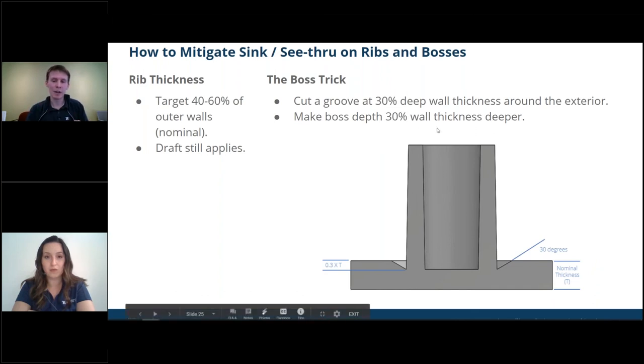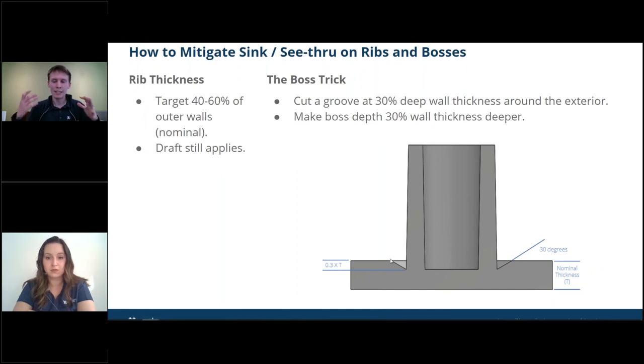And you could do that by thinking about your part as 100%. If you make the inside of your boss at that 30%, so again, if I'm talking about something that's 100 thou, and I make my boss 30 thou deeper, as well as create a groove that is 30 thou deep and then goes up 30 degrees here, so basically a ring around the boss there, you can actually significantly mitigate and sometimes negate sink showing through on those parts. It's a really neat trick.